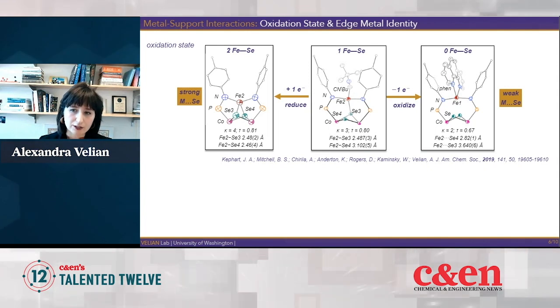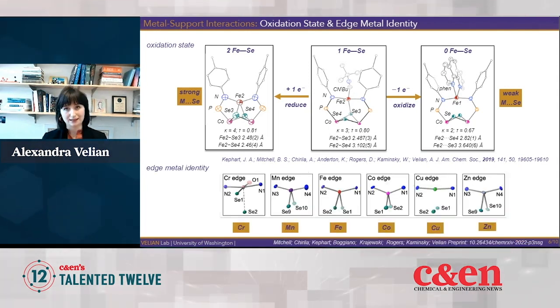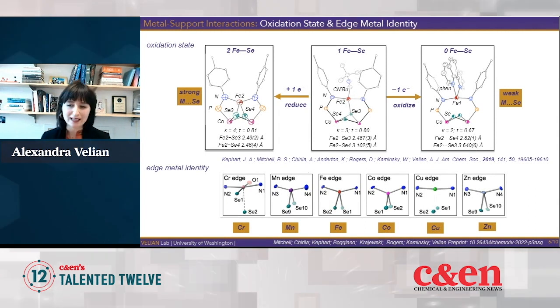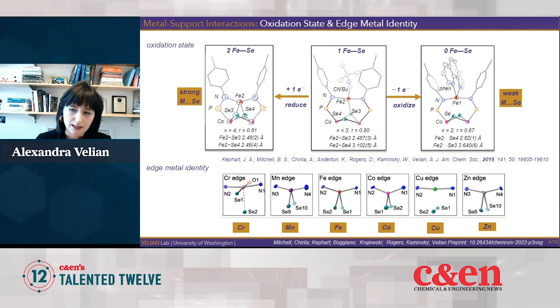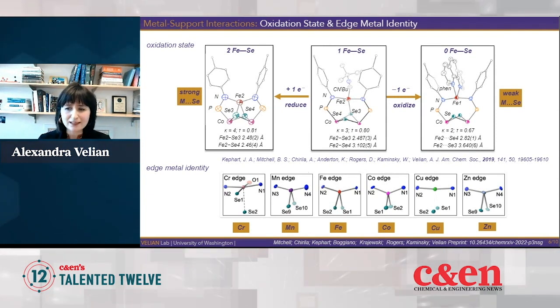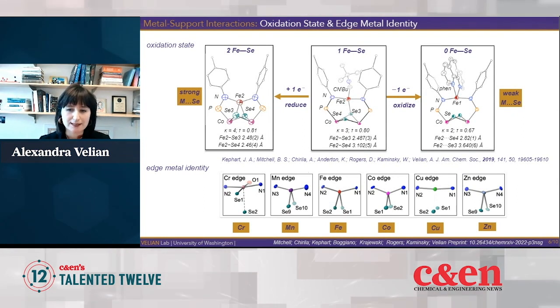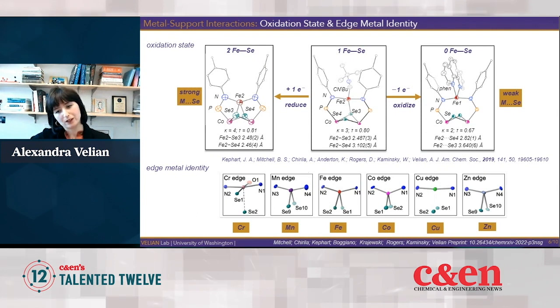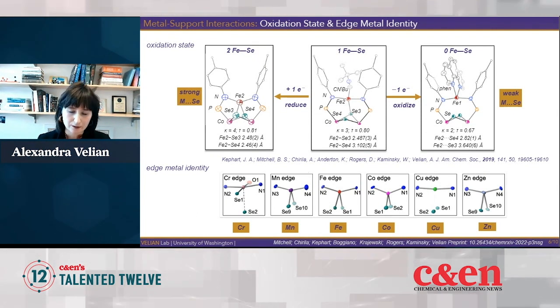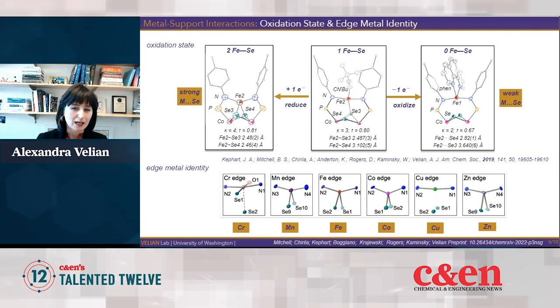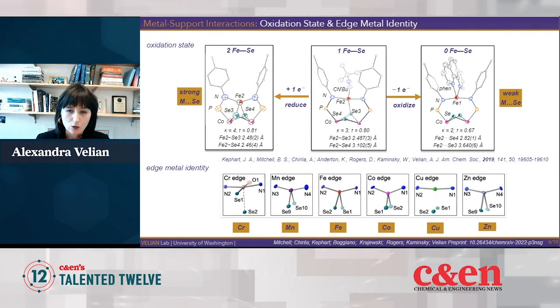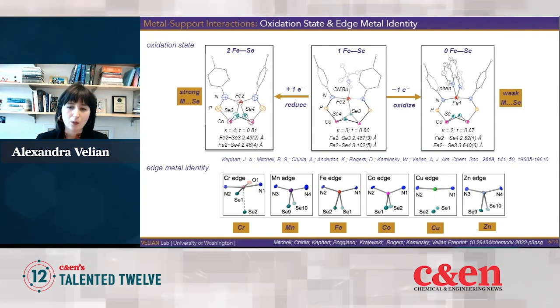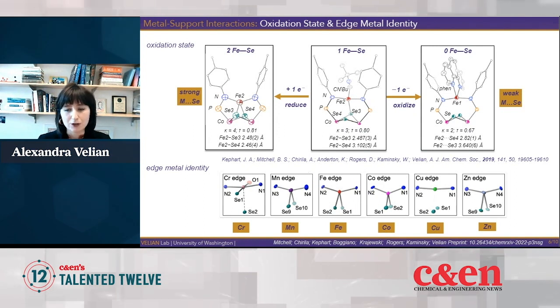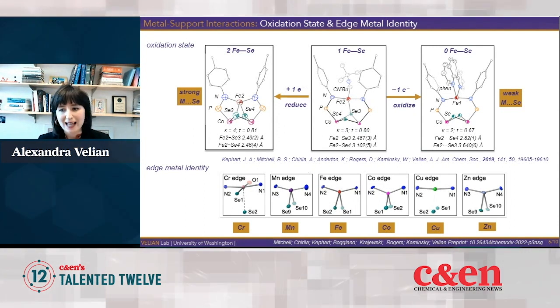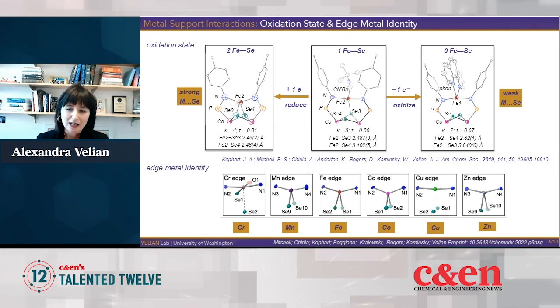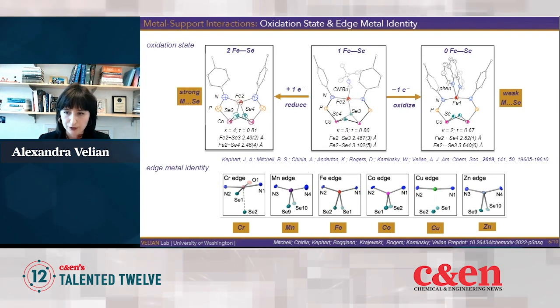Another thing that can really change the strength of this metal support interaction is the metal identity itself. And we looked in great detail to understand this, but this is really to showcase the flexibility of this cluster support as a ligand framework, essentially. So going from chromium to zinc, we can observe the surface of the cluster restructuring slightly to accommodate the preferences of different metals. So for chromium, you have the square pyramidal coordination environment with an external ligand bound. Most of the metal edges, like iron, manganese, etc., have a pseudotetrahedral coordination environment. And then here's copper, which adopts a linear one, really a result of charge transfer with the cluster.